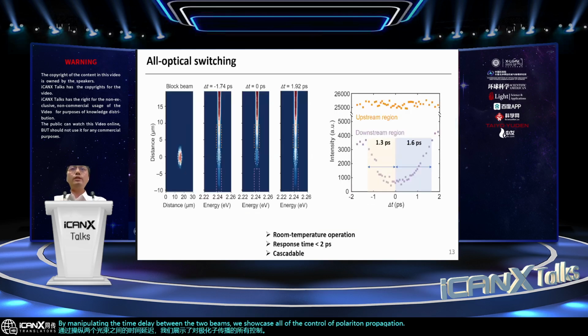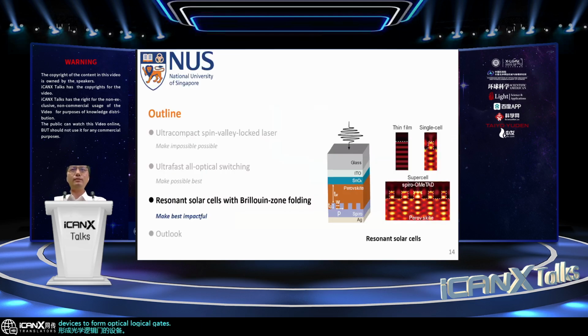The real space image indicates that the polariton propagation stops upon synchronization of the two beams. However, with a time delay of more than 2 picoseconds, polariton propagation recovers. The propagating polariton fluid also suggests that this all-optical switch can be cascaded with other devices to form all-optical logical gates. To transition nanophotonic innovations from concept to